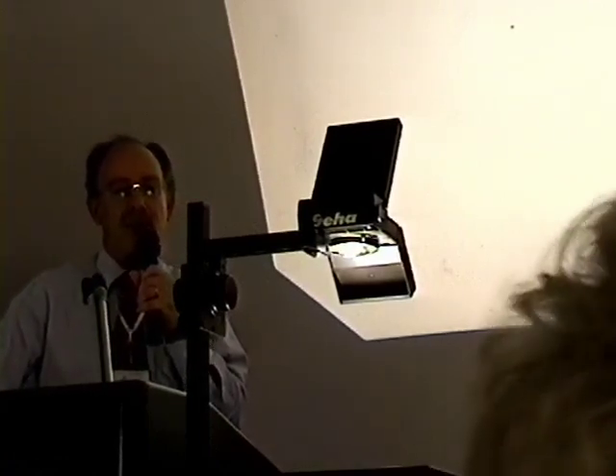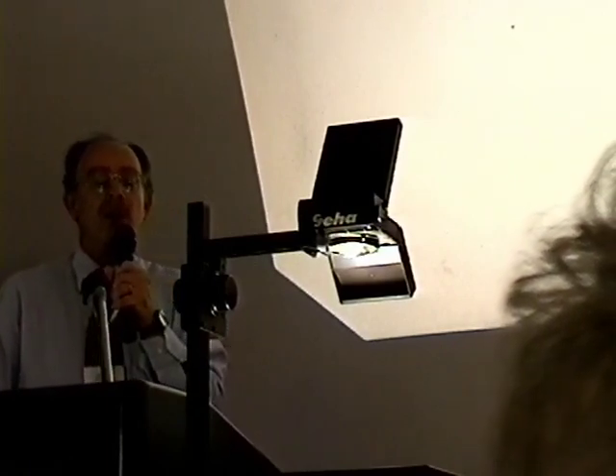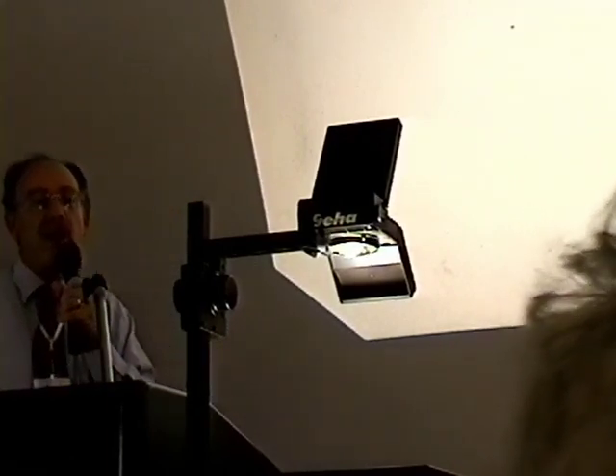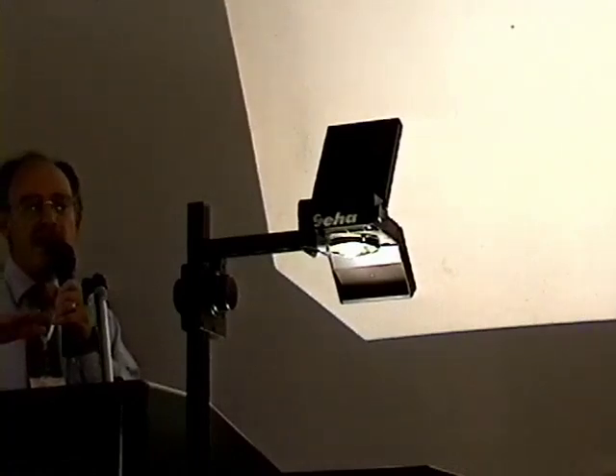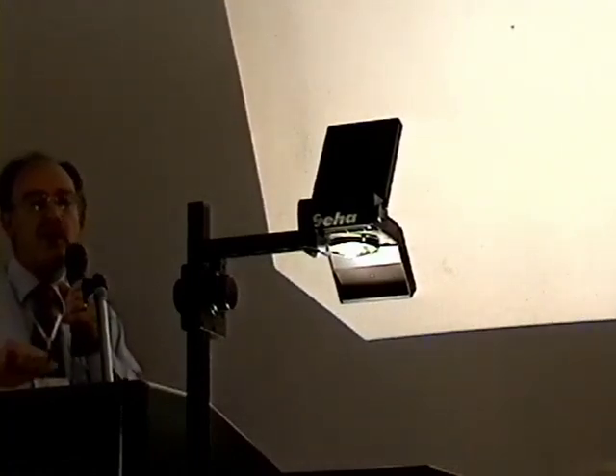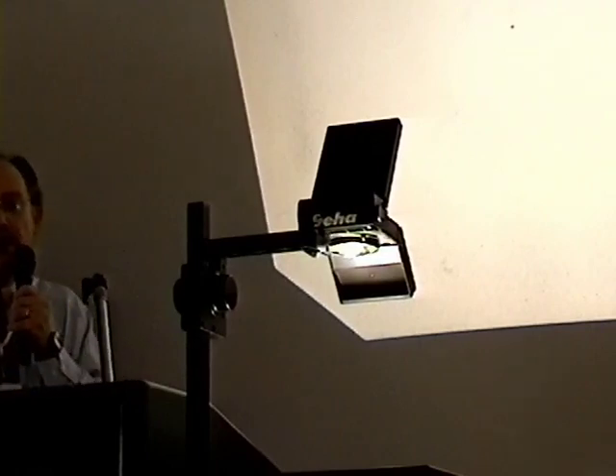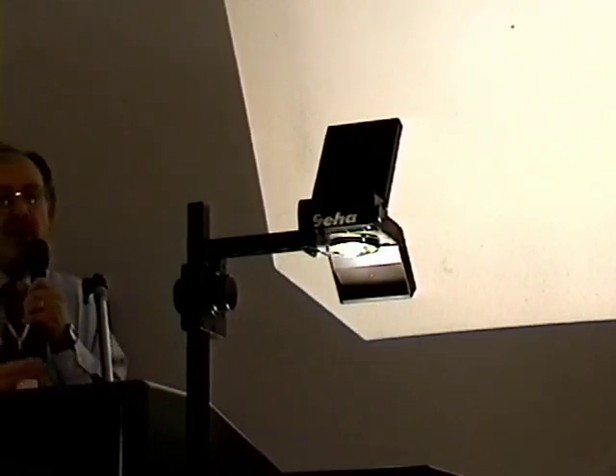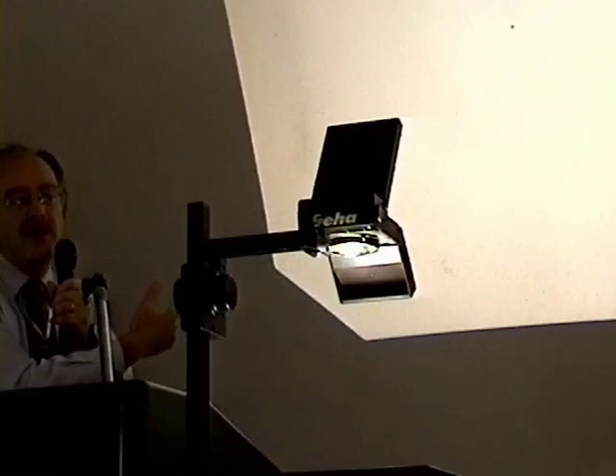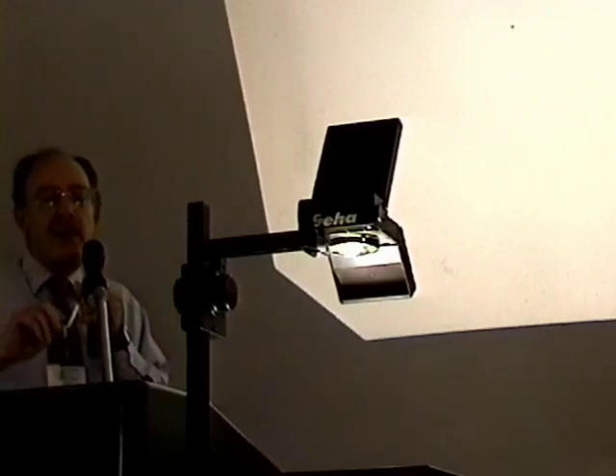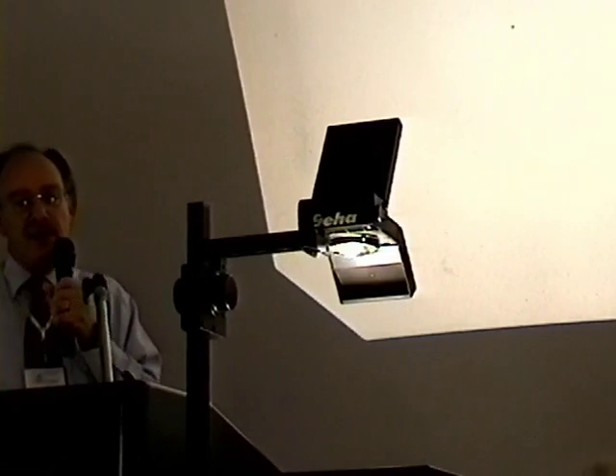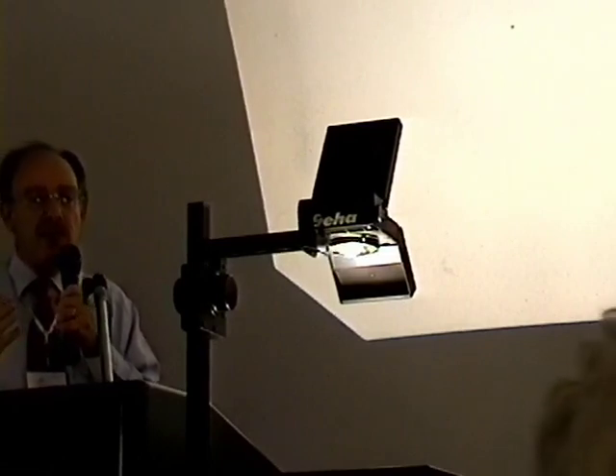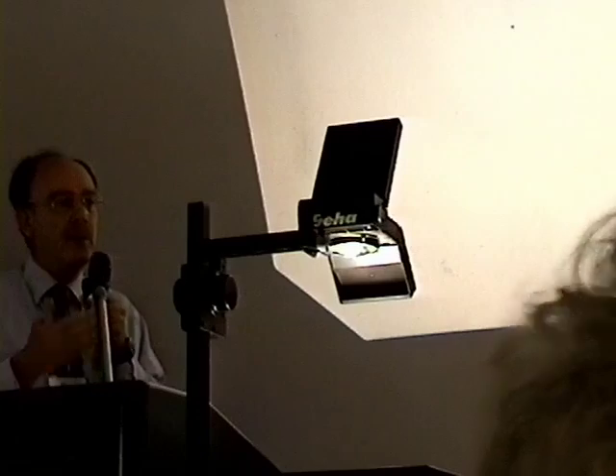Would you like to see a spectrometer? It's not during the measurement, it's after. No, when we deposit the film, we can check the film and we can check the content of boron, phosphorus, all the ingredients we have inside the film. In this case, we have silicon nitride and silicon H and nitrogen H bonds. We can measure the number of bonds with infrared spectrometry. Thank you.